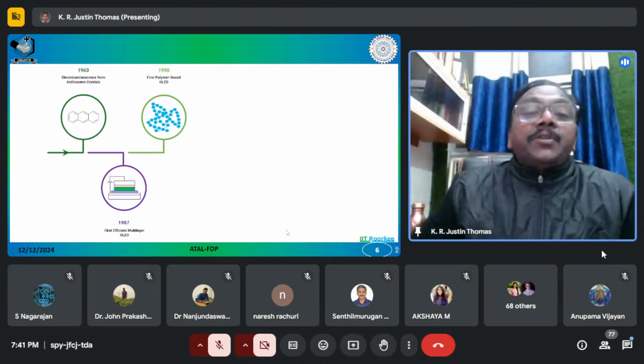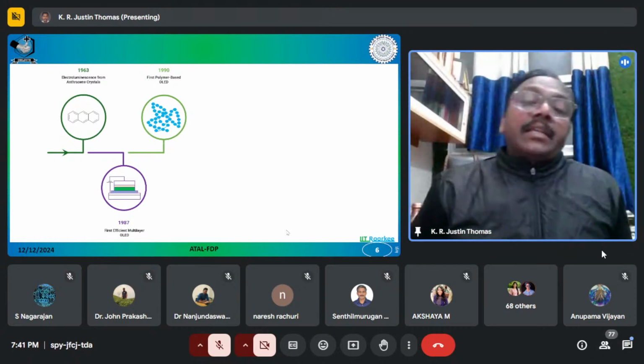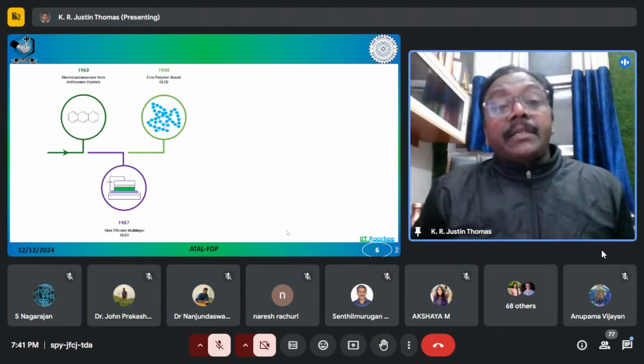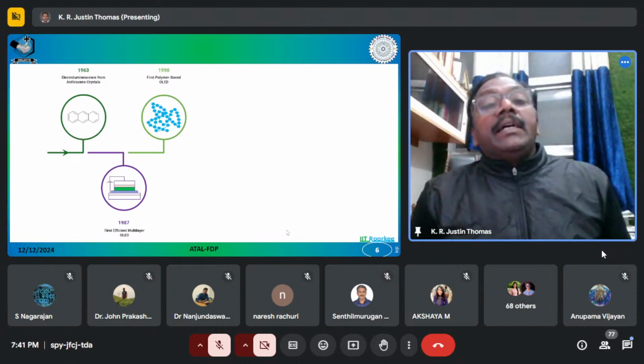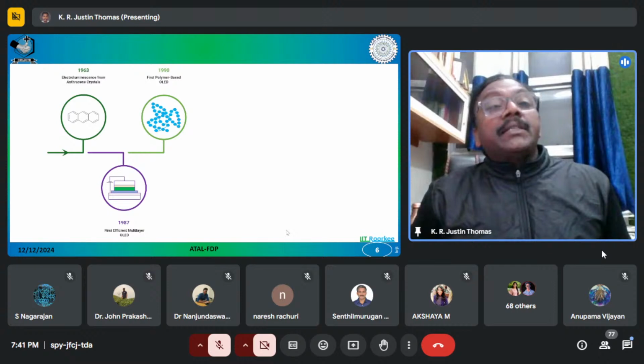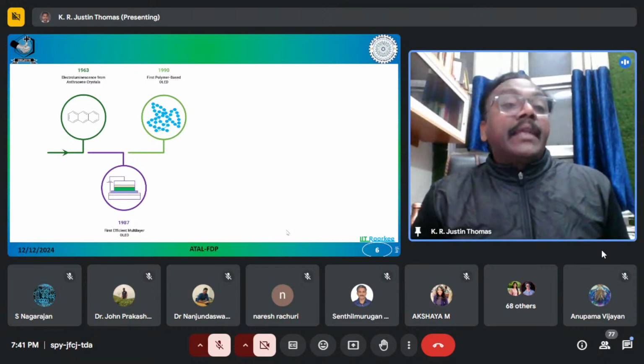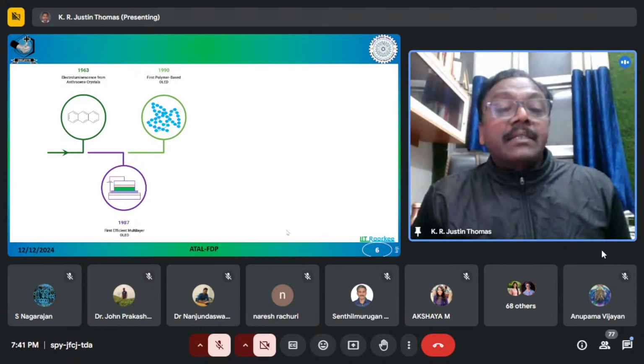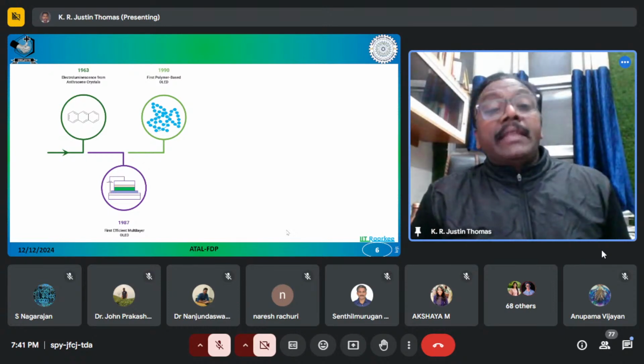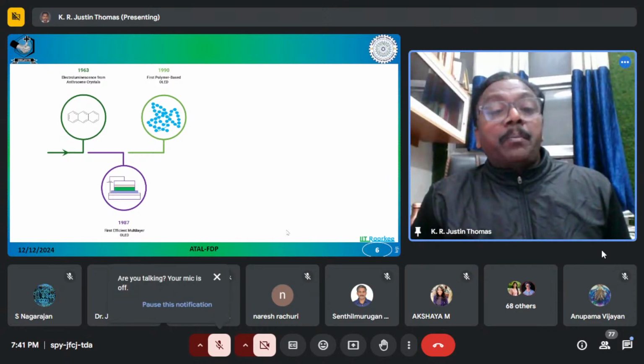Now, as I have already told, since the fluorescent materials are not capable of harvesting triplet excitons, people then looked at organometallic molecules, because the organometallic molecules contain heavy metals such as ruthenium, osmium, iridium, platinum, and so on. So they normally undergo facile spin orbit coupling, and that facilitates the intersystem crossing.